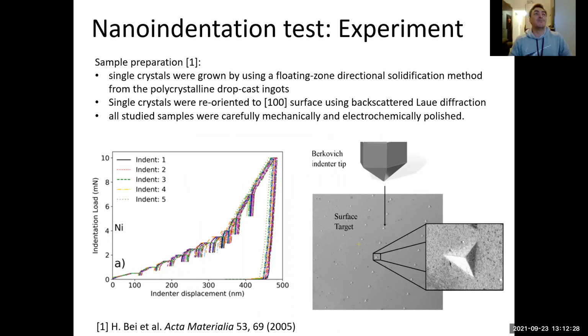Thank you so much. So in the nanoindentation experiment, this is how they prepare the SP-CSA materials. A single crystal was grown using a floating zone directional solidification method from the polycrystalline drop cast ingots. Then the single crystal is oriented to the 100 surface using backscattering diffraction. This information on the 001 crystal orientation is very important for the numerical modeling. Sometimes we use this information to know the crystal orientation to perform the MD simulations. The materials that we have here and the results that I'm going to present are only for the 001 crystal orientation, for the experiments and for the numerical modeling.